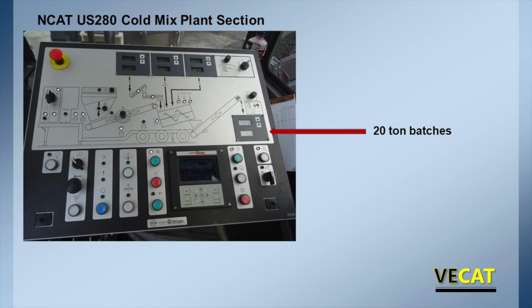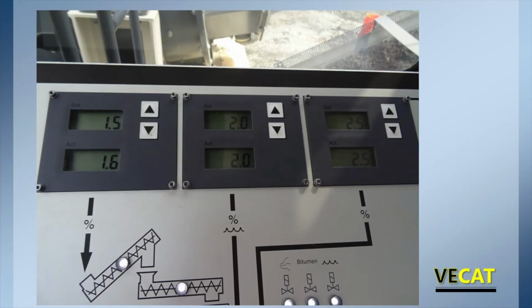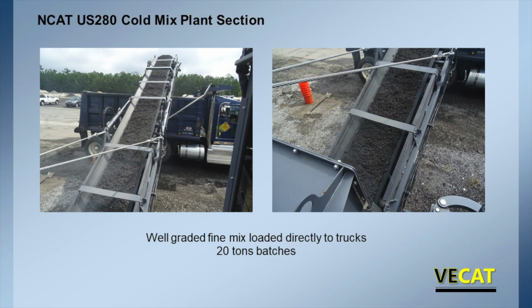So our mix, we're now working in 20-ton batches. We've put in 1.5% cement, 2% water for compaction, and 2.5%, that would have been foamed asphalt section. The emulsion was 3.3. So we're 1.5, so you'll see a little fluctuation. These things are always hunting, but nominal 1.5% cement, 2% compaction water, 2.5% bitumen, that was foamed asphalt. So that is your deal, don't change it. Load into trucks, you can see here, even while it's moist, it's not looking like asphalt.